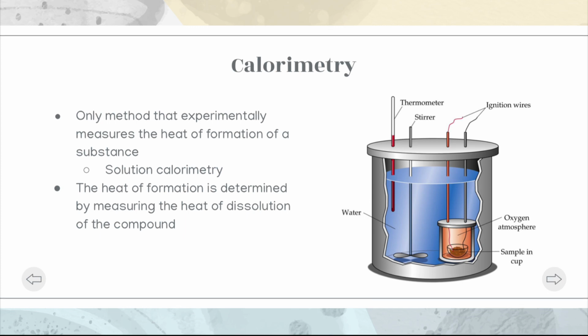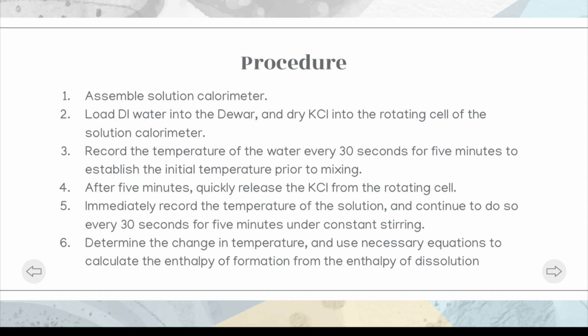Alternatively, the lattice enthalpy of KCl can be determined using yet another extension of Hess's law. In this calculation, the enthalpy of formation is determined by adding the enthalpy of dissolution of KCl with its enthalpy of hydration. Because KCl does not easily form hydrated complexes, we can use values from the literature rather than determining this value experimentally. The following slide provides a step-by-step method regarding how to take calorimetric measurements.